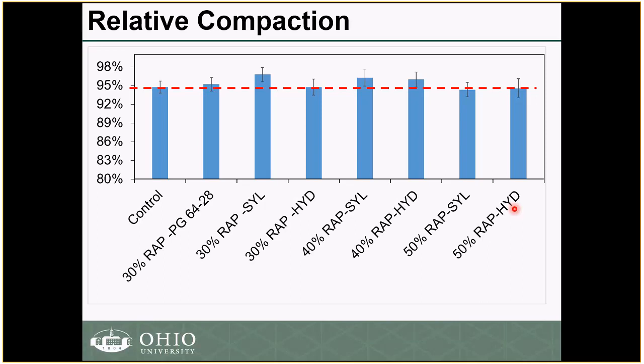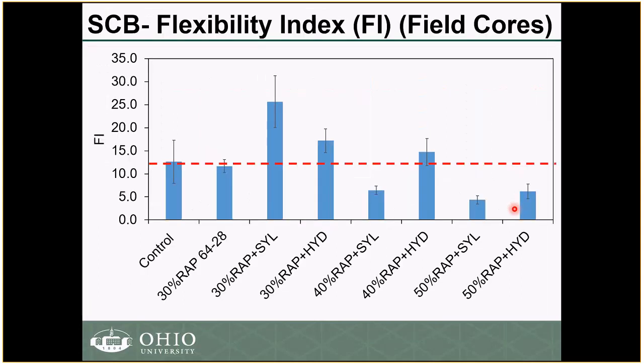Regarding relative compaction, you can see that in general, densities were very similar across the different sections. The compaction effort and compaction patterns didn't change between the sections, so we were able to achieve the same density with the same compaction pattern. Okay, so the results here are for the field cores.